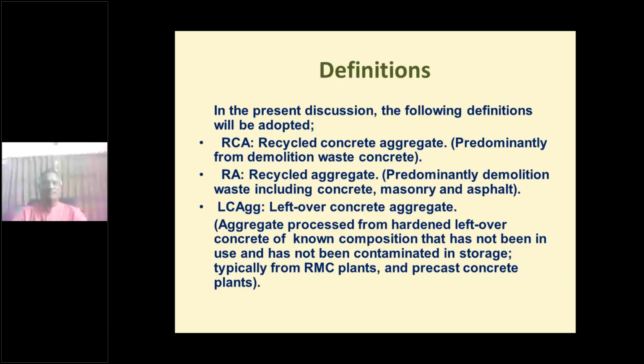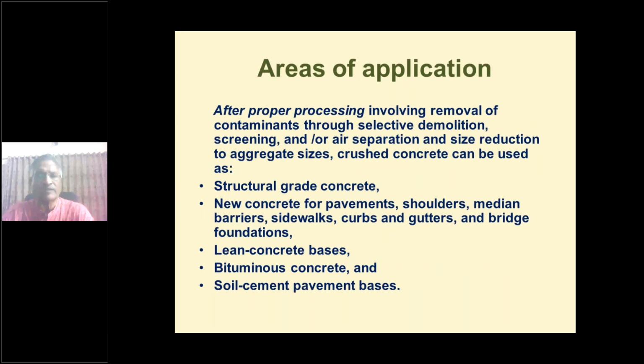So at present, we have two types as per the code 383, RCA or the recycled concrete aggregate, which is predominantly from concrete waste, and recycled aggregate, which is from all kinds of waste, including masonry and asphalt. Leftover concrete aggregate is also there, that is used for very minor works. After proper processing, it can be used for structural grade concrete. We can use it up to certain restrictions and percentages.